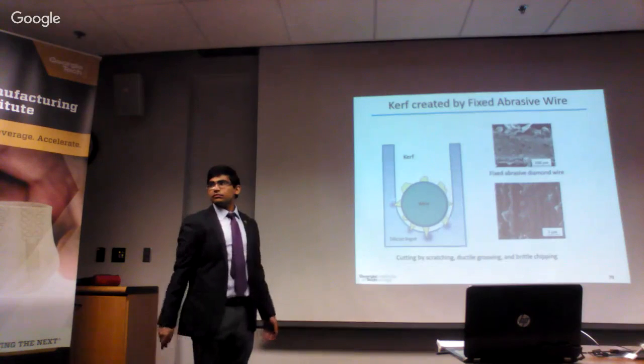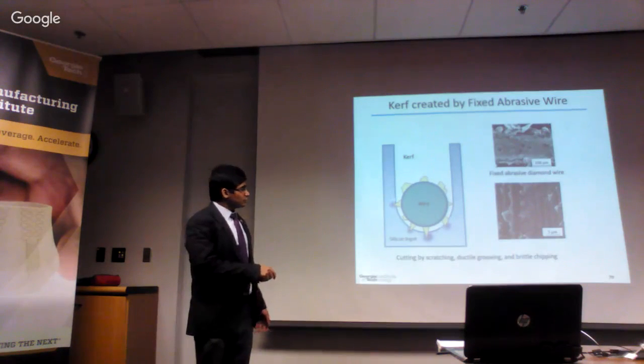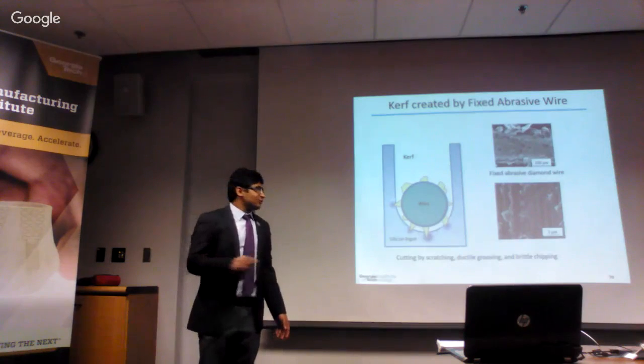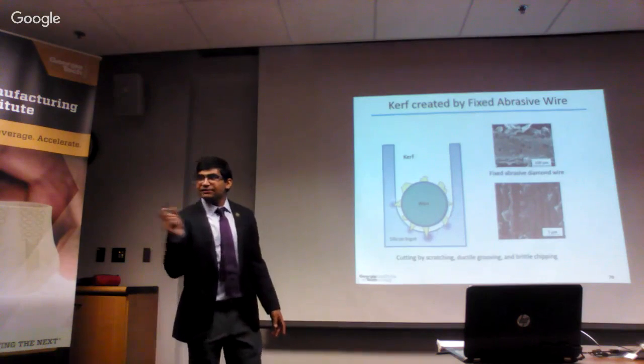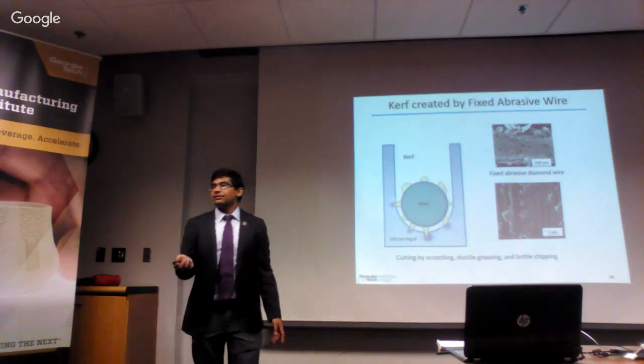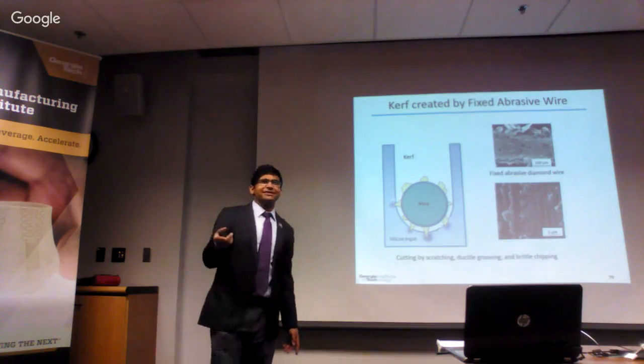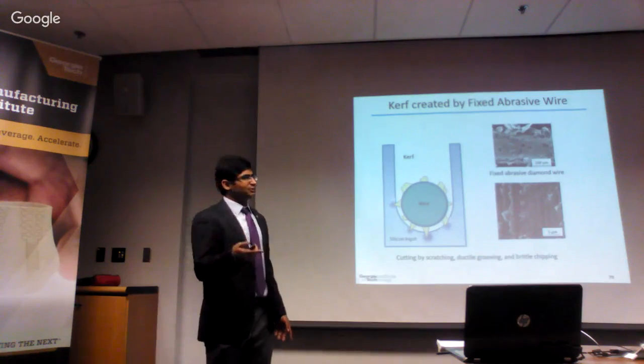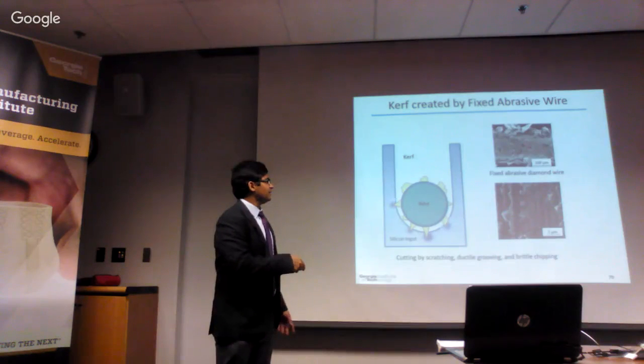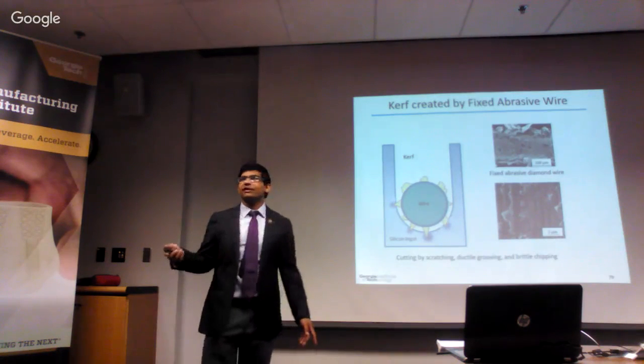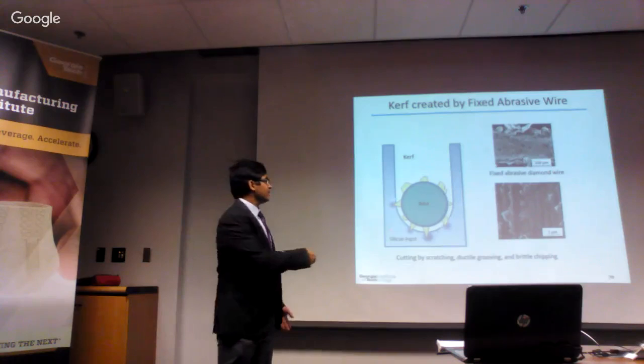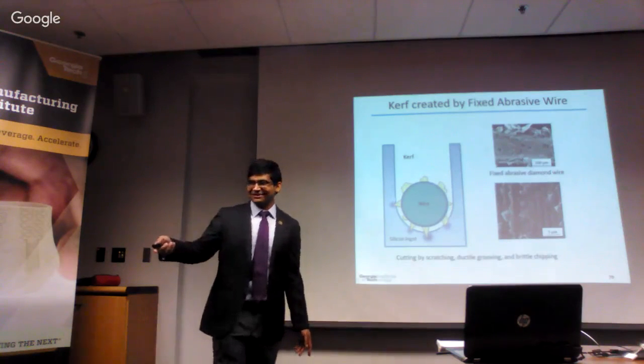But what if the lateral crack right underneath the wire is big enough that it goes into the wafer? So the wire size is 140 microns. The crack size is 10, 20, maximum 40 microns I've measured. So half of 140 is 70, 80 microns. It won't go into the wafer. But we did talk about this earlier.